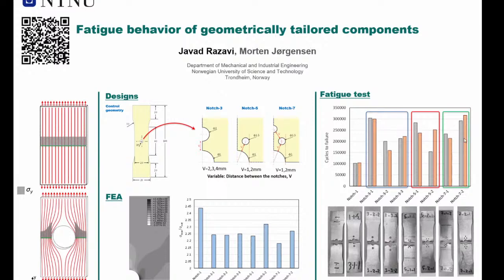So this doesn't quite follow what we saw in the linear elastic analysis that we performed, but overall, it was quite hopeful for us to see that even by adding a small notch that has a radius of 0.7 millimeter, somewhere around the main notch, we could manage to increase the fatigue life 3 times. Of course, this is not a general statement.